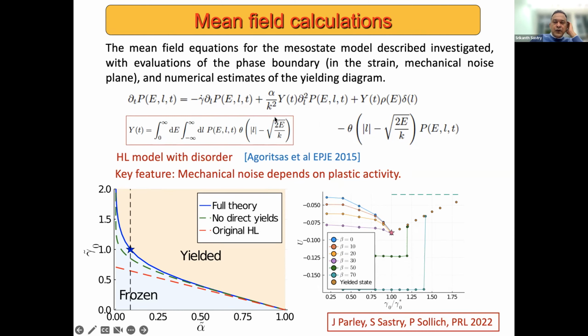And with this description, one can go ahead and look at where the stability boundary is. There's this additional parameter alpha, which also controls the diffusion coefficient. With respect to the strain amplitude and alpha, one can construct the boundary between the frozen and the yielded states. One can also numerically obtain a yielding diagram, which once again looks like what we've seen in simulations and in these standard models.